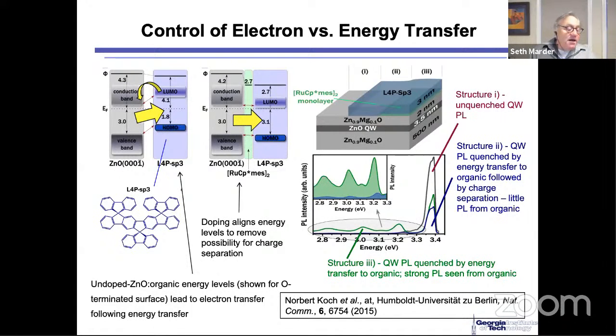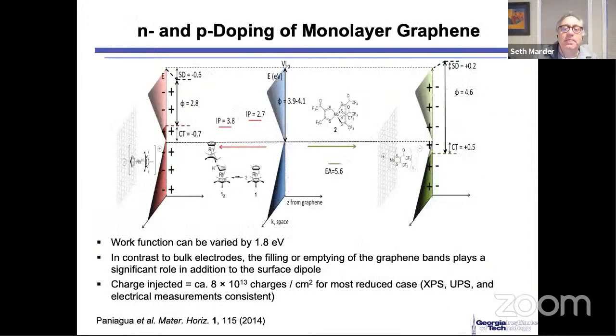So here again, in the toolbox, they made these two materials. They had almost everything that they needed. And I would say in this case, the dopant worked a little bit like sandpaper. It allowed you to just slightly tune the property to give you the band alignment that you needed, as well as leading to a relatively low injection barrier to inject electrons if you wanted to. That's a separate thing.